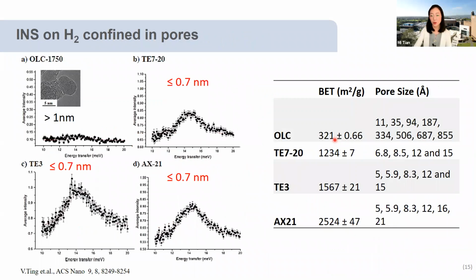Then we want to know what kind of material will work. Will all nanoporous materials work for hydrogen densification? Surprisingly, we found not all the materials work, and only materials with very tiny pores, with pore size less than 0.7 nanometer, can densify and solidify hydrogen at this condition. For example, this material is onion-like carbon, which has bigger pores, larger than 1 nanometer. You can see it from this TEM image, and it doesn't have the ability to solidify hydrogen at this condition. So now we know the pore size plays a key role.